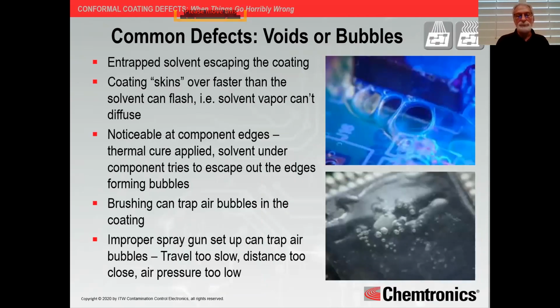Voids and bubbles, okay? Bubbles are essentially caused, for the most part, by solvent that has flashed off. Now it is vaporized and is trying to escape that coating, and it can't. So it bulges that coating. What happens is that coating skins over faster than the solvent can flash, and it's trapped. It will slowly diffuse out, but now that coating is cured just enough to maintain that bubble shape, and it can create a void.